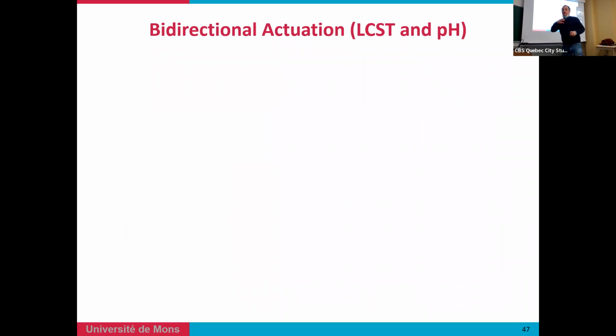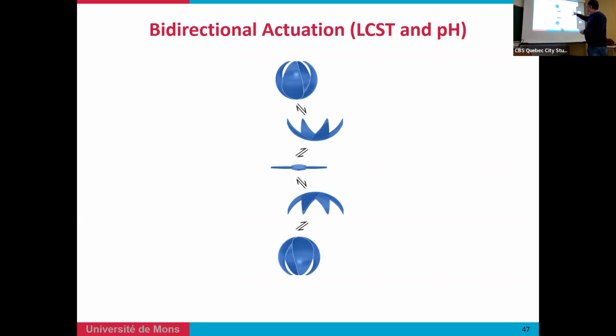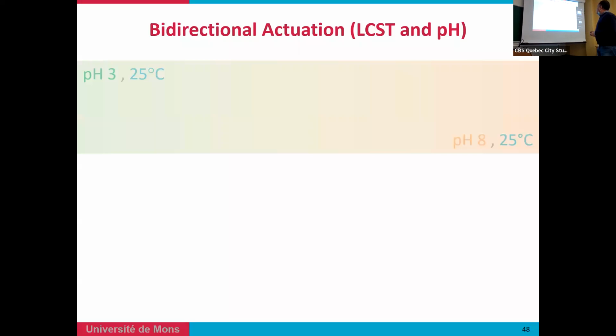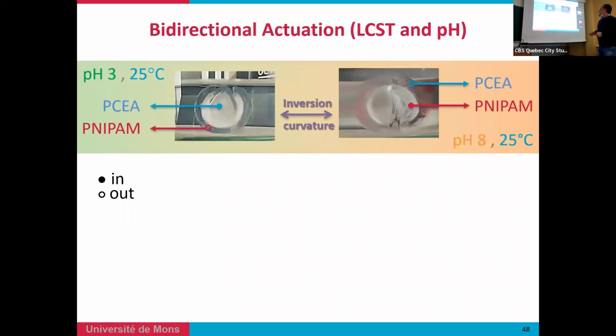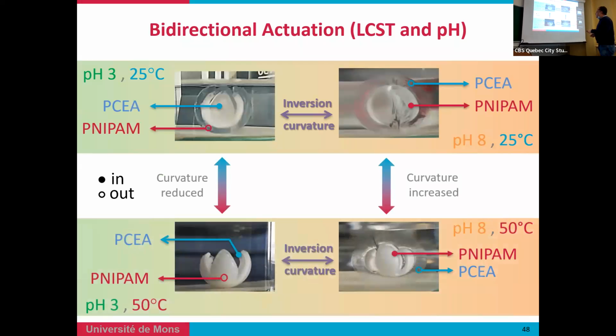Of course, this is difficult to show, but by playing with the temperature and the pH, you can have a real bidirectional actuation, meaning you can have this movement at the top but also at the bottom. The problem is the gel is not well adapted for such swelling, but you can show this bidirectionality. In practice it's quite difficult, you have to believe me, but playing with the pH at the same temperature, or using temperature by changing the pH, you can have this bidirectional movement. But because of gravity, it's not easy to see based on this picture.